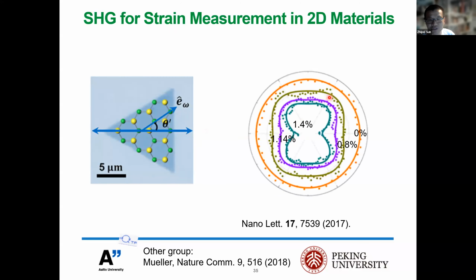At the moment, many people are also discussing how to use strain engineering to change the optical and also electrical properties of 2D materials. Here we are working with Professor Liu from Peking University. We demonstrated that second harmonic generation can be very useful to measure strain vectors. For example, this is a CVD flake we used. We applied the strain along the armchair direction. Then we measured the second harmonic generation response as a function of the strain.